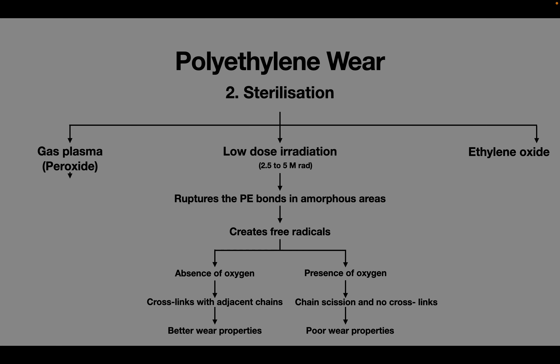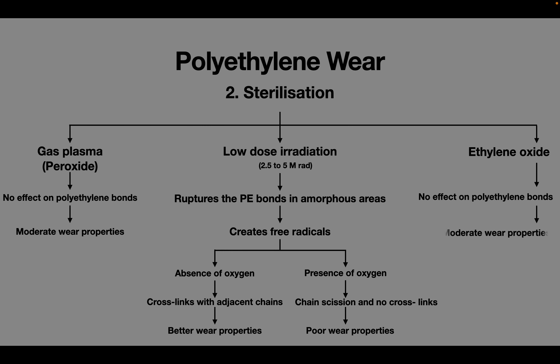Polyethylene sterilized by gas plasma or by ETO does not produce free radicals and hence no cross-linking. Such polyethylene has moderate wear properties. Following sterilization by gamma irradiation, polyethylene is packed in vacuum or in an inert atmosphere.